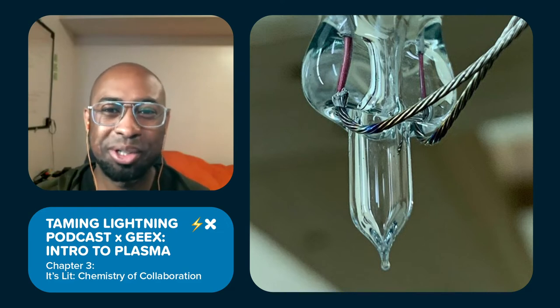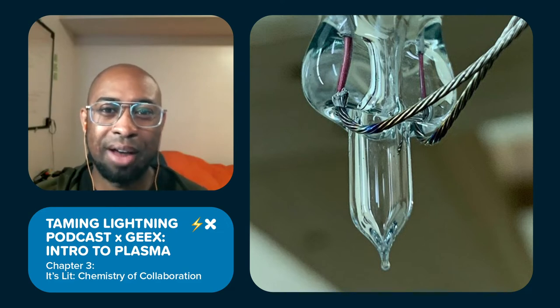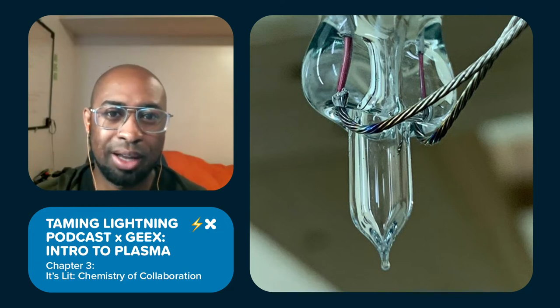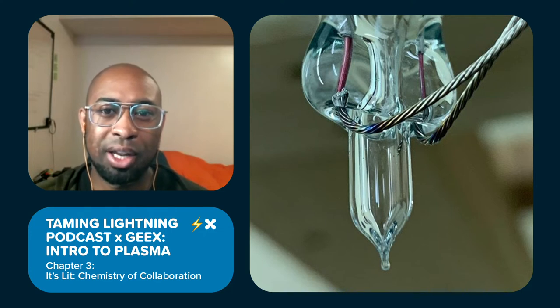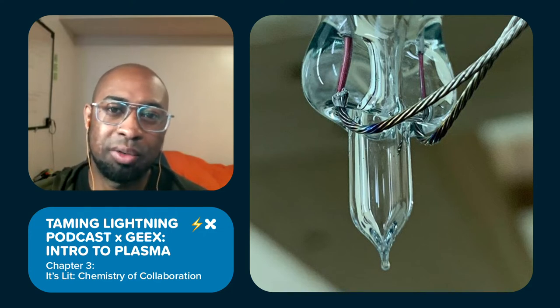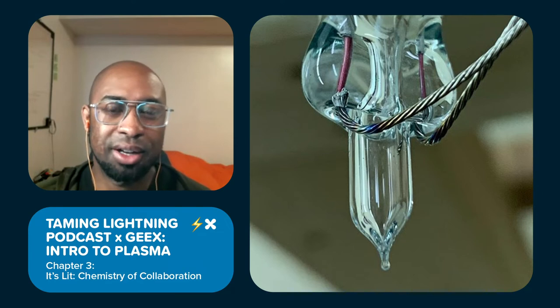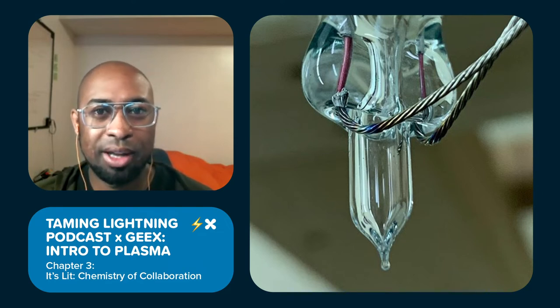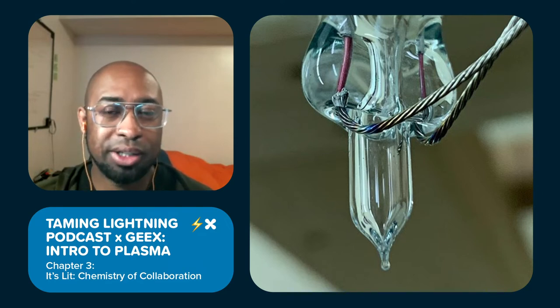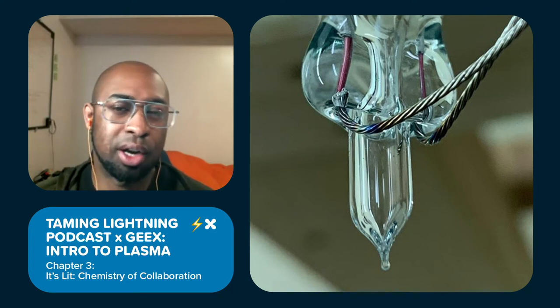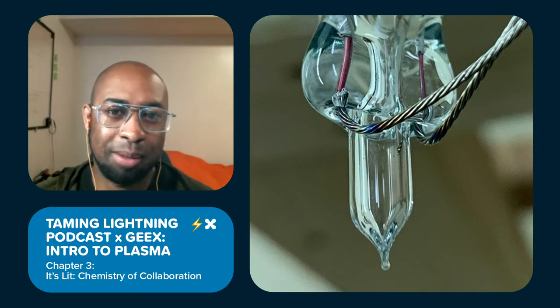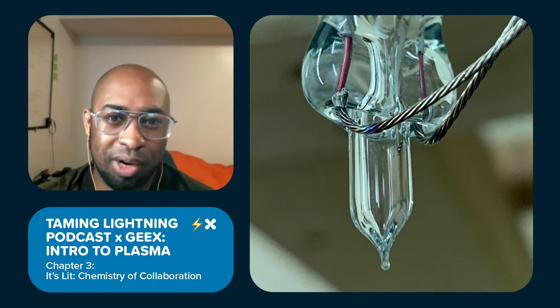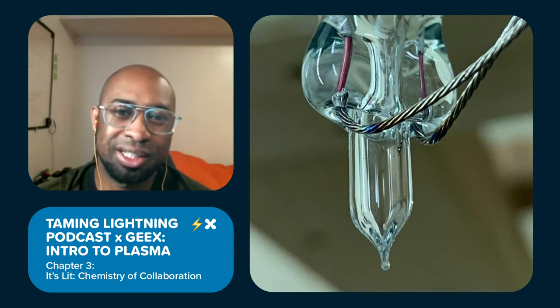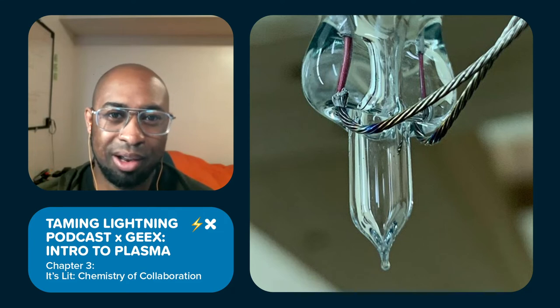To execute the borosilicate tip-off, try to have your constrictions pre-planned. It'll make it a little bit easier on borosilicate because they do not flow as much as soft glass does. So in the same way that we tip-off twice, perhaps prepare two areas with constrictions so you may have the same option. And most importantly, you want to do this move once and move on. Tip-offs are incredibly sensitive to reheating and reworking.